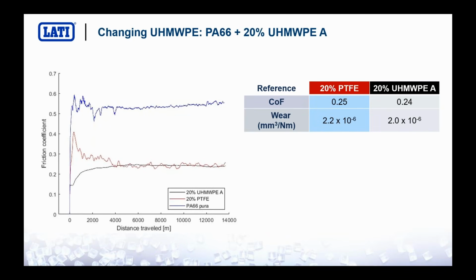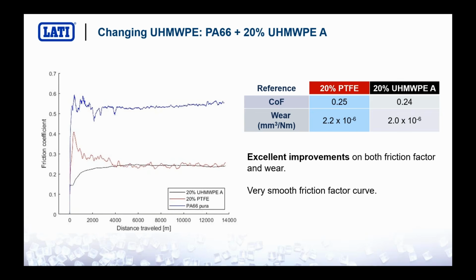Now let's have a look at a very good result. So the use of another kind of ultra-high molecular weight polyethylene optimized for tribological properties. As you can see, we obtained in this case, this was a very, very good result, the same values in terms of friction coefficient and wear resistance of PTFE. And as you can see on the curve, it is very flat, very smooth compared also to the PTFE. So this is a very, very interesting result that we obtained.